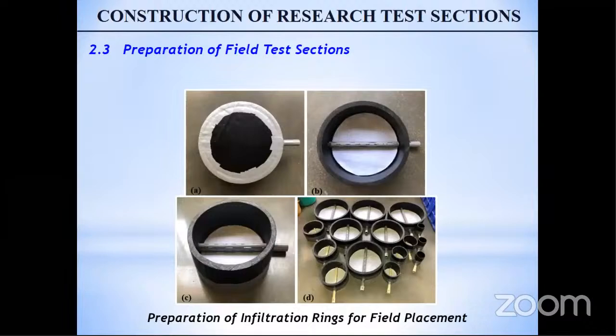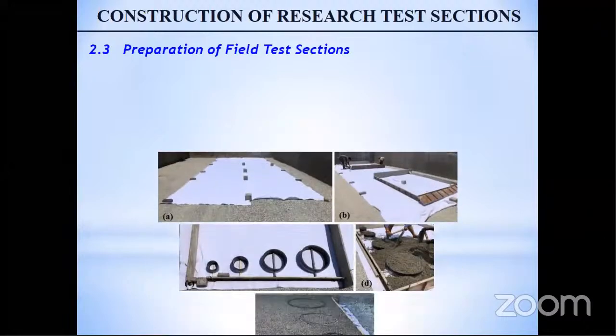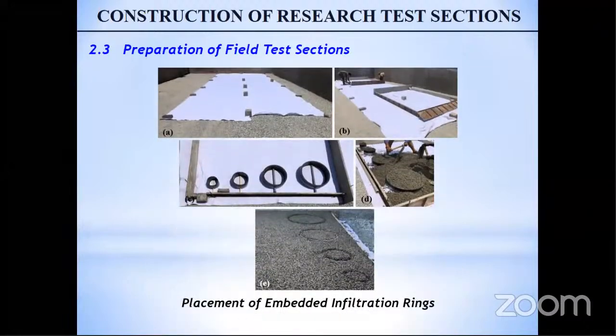You can see this is how the infiltration rings were placed. They were actually sealed at the bottom with the geotextile materials. The objective was to seal the bottom so that water doesn't intrude into the lower layers. And the second aspect was to ensure that the aggregates from the lower layer as well as the top surface do not puncture. So once all of these infiltration rings were prepared, they were actually laid onto the test section. As you can see, the pipes were actually placed adjacent to the formwork, and fresh material was poured into it and compacted in a similar fashion as we do for the construction of the pervious concrete layer.